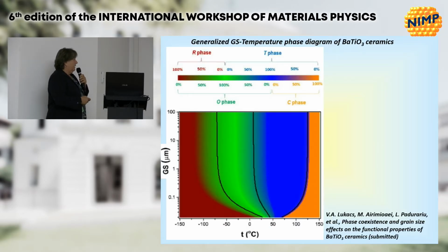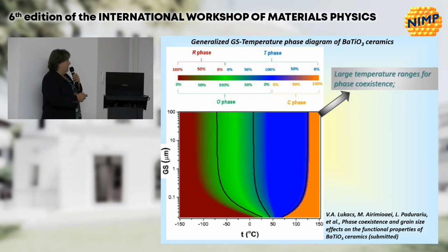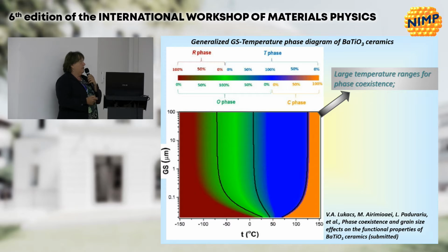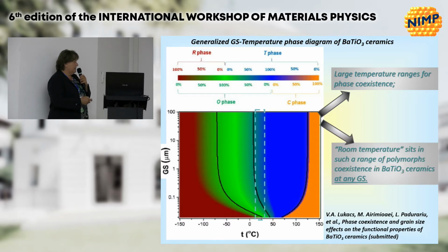I was speaking about looking at the metastable free energies instead of only the absolute minima of the free energy. You find quite large ranges of phase coexistence, which are represented here by this mixed color. For example, this color corresponds to 50% rhombohedral and orthorhombic phase in this range that accompanies the main transition, which would be the transition corresponding to the minimum of the free energy only. Well, we have therefore large temperature ranges for phase coexistence, and as experimental data also have shown, room temperature sits practically in such a range of polymorph coexistence in barium titanate ceramic at any grain size.